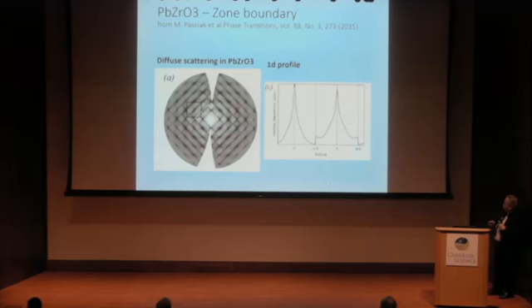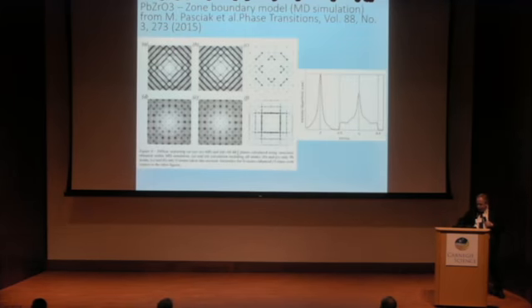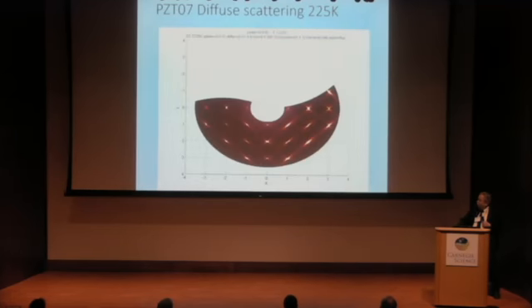close to the endpoint, at some arbitrary temperature, I don't remember what it was, we see something very strange: we don't see the peak at the endpoint. We see some low intensity on one side and high intensity on the other. It was later demonstrated by molecular dynamics simulation that this peak could be simulated only if we take into account both, let's say, lead displacement and oxygen displacement.